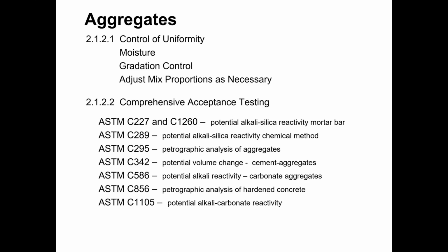All right, acceptance testing of our aggregates. A number of ASTM tests that can be used for acceptance testing are shown there on your screen. There are many, many more that can be used. It seems like every few years there's another ASTM test that comes along that can be used to evaluate the acceptable performance of an aggregate within concrete. So these listed here are the ones that have been around the longest, but there are others that can also be used. Some of these are long-term tests that may take a year to complete.